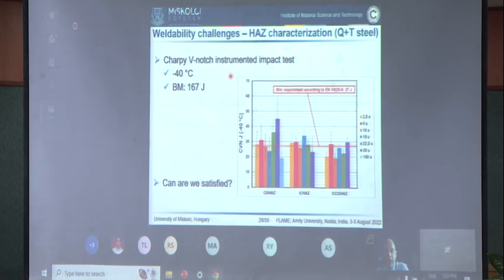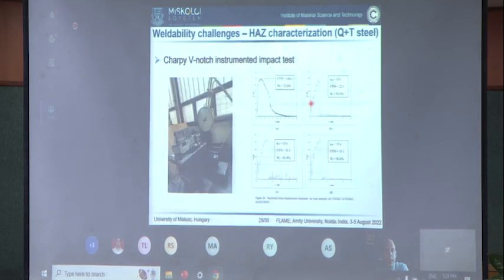Regarding the impact energy and the Charpy V-notch test results, we can say that there is a very significant toughness reduction in the heat-affected zone. Just imagine, the base material often has a toughness of even 160 joule at minus 40 degrees, but generally the impact energy values decrease to the level of the limit of the governing standards. The question arises whether we can be satisfied with this kind of impact energy in the heat-affected zone. In my opinion, we cannot be fully satisfied.